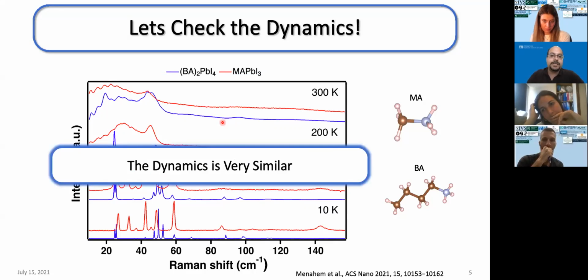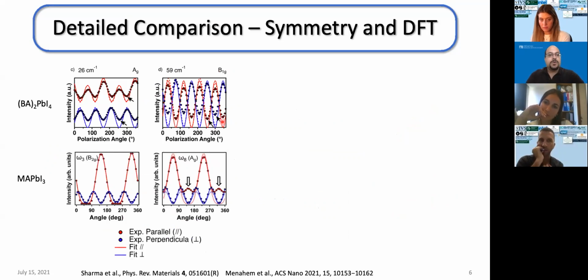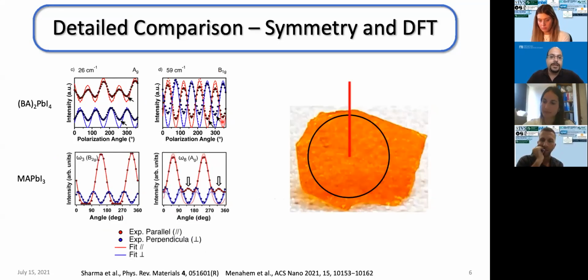Now, again, all of this tells us that the structural dynamics of methyl ammonium and butyl ammonium are similar, and that our initial hypothesis, that the comparison has merit, is valid, and we can go on with the comparison. So we went to a deeper analysis using a method called polarization orientation Raman scattering, where we excite our